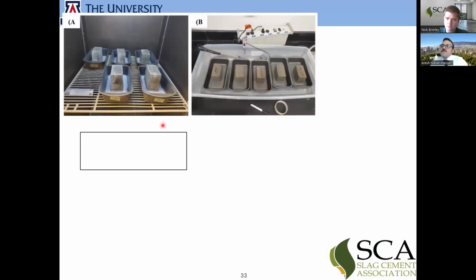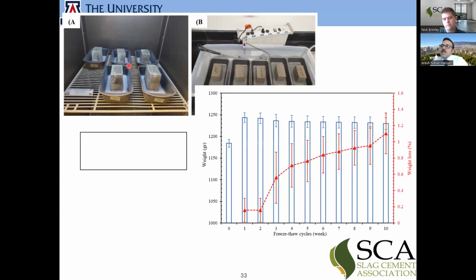So we put the samples in the freezer and decreased the temperature to the freezing point, then took the samples out after 24 hours, put them in a melting zone, and kept them in water for 24 hours, and then we checked for weight loss. Basically, when we take the samples out of the freezer, we want to see if the weight of the samples is decreasing. That would mean the materials are losing their integrity and the particles are washing away. We tested the samples for 10 weeks, and each week we did 5 cycles during the weekdays, so we did 50 cycles on the samples.